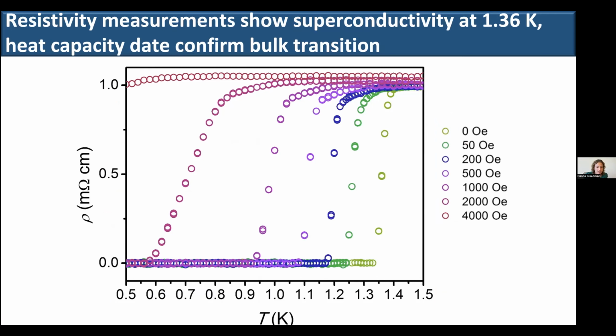And here we have resistivity versus temperature. For superconductivity, the hallmark is a transition to zero resistivity, which is magnetic field dependent. As we increase the magnetic field, the Cooper pairs that comprise the superconductor start to break and preferentially align with the magnetic field rather than each other, leading to the superconducting transition moving to lower temperatures. And this material clearly demonstrates that.